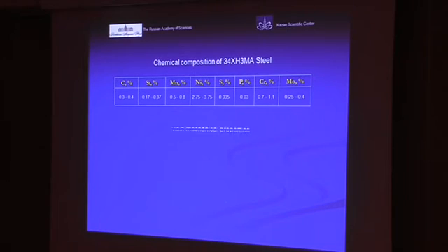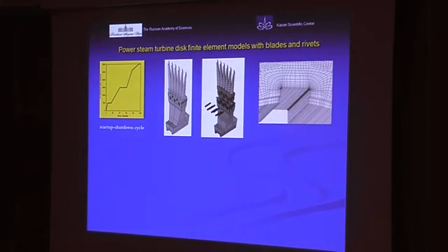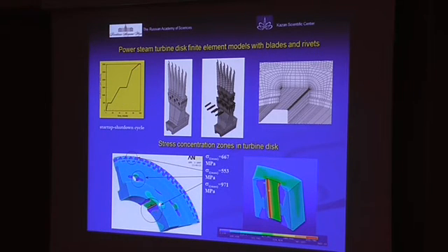So, first of all, we carried out the finite element method to determine elastic plastic stress and strain distribution at operation loading conditions. The operation loading condition is a startup-shutdown cycle. And we have found that the maximum equivalent stress is realized at the deepest point of the slot face, and the maximum value of equivalent stress exceeds the yield stress of the material.